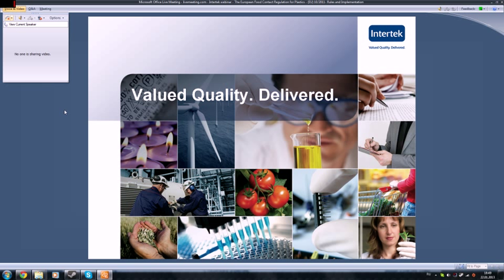Okay. The next one: when talking about food contact time, the period and the temperature, is this what the manufacturer expects under normal use conditions? What about frozen food and storage containers? Well, if you use storage containers, let me respond to that first. If you have repeated use, you can make 3 migrations in a row, every time changing the solvent. If it shows that the migration figures are declining, then you can use the third figure for compliance with the SML given by the PIM. Important is why it should be shown that it's declining: in some cases there could be a degradation and the migration could be increasing. That's why you need to measure all 3 values, but you can take the third one for compliance.